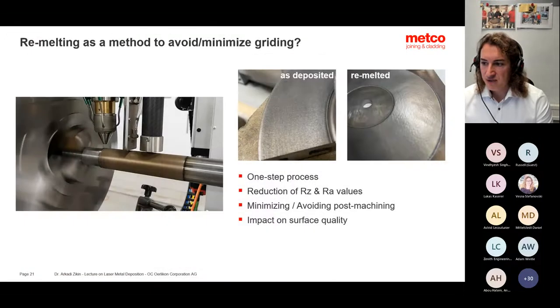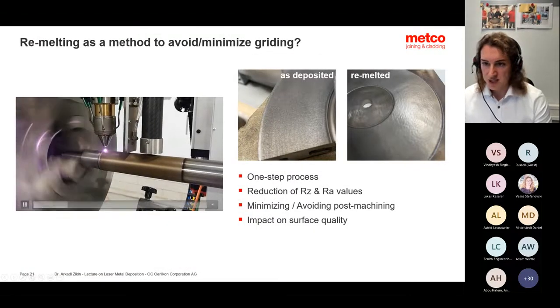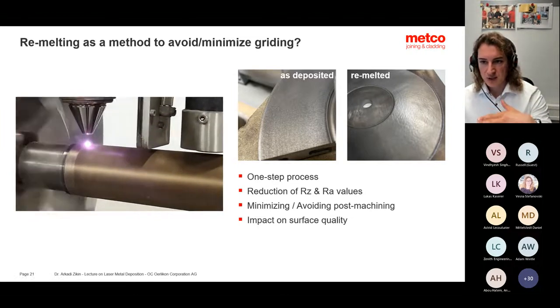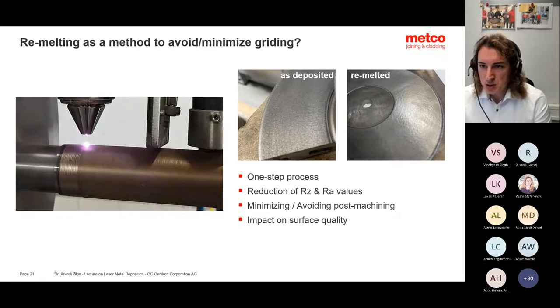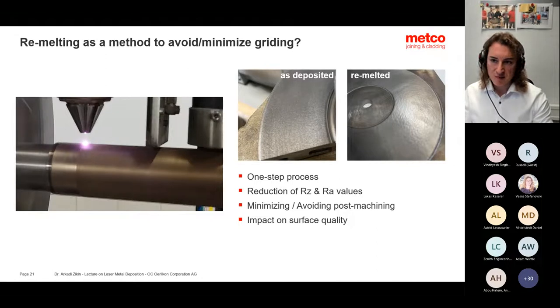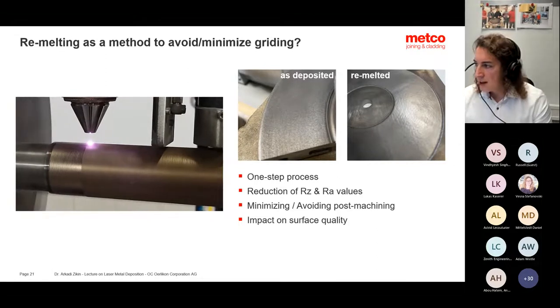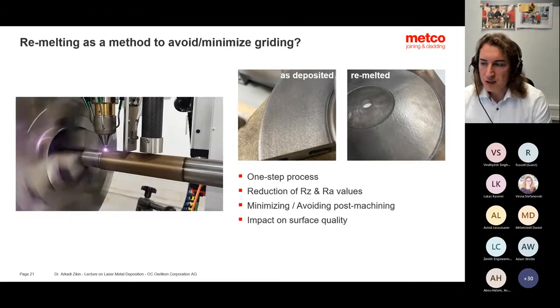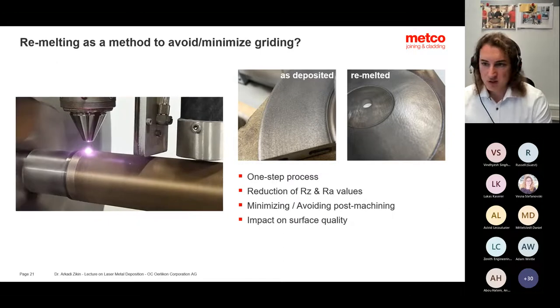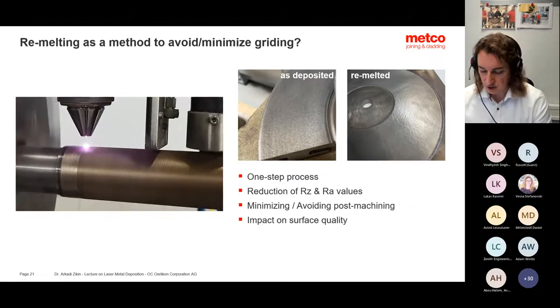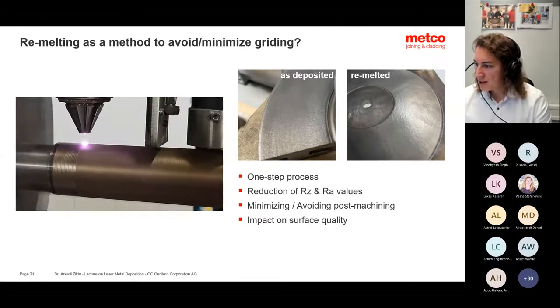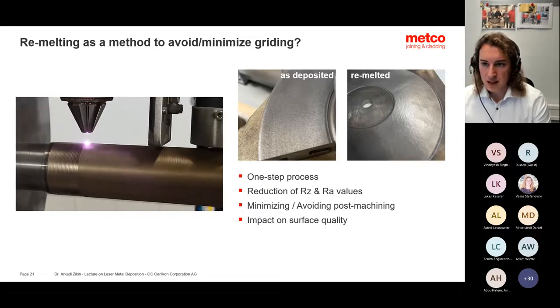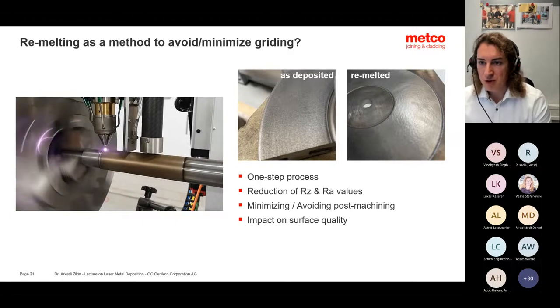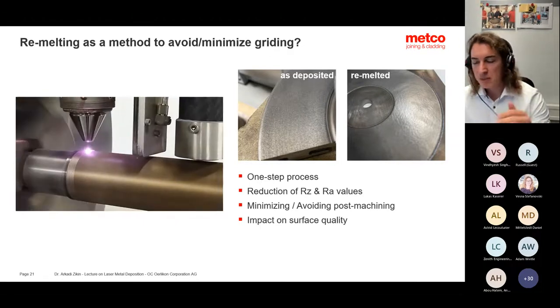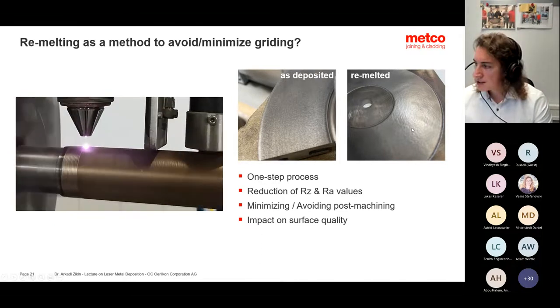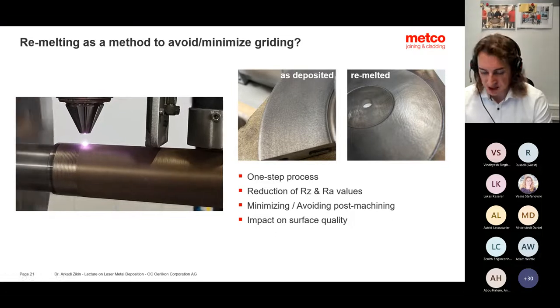And you can also move one step further. By doing that, you can, for example, remelt the surface using the same process without interaction with powders. And the main advantage you can get out of this is that you just smooth the surface, taking certain asperities away or some stuck powder particles. And for certain applications, you can completely avoid any type of post-treatment if a surface quality of something like Ra 5 would be enough for you. I believe there is still a lot of work moving in that direction. And we also recognize that working with laser surface remelting requires process understanding and development steps. But at the end of the day, you can get results which look pretty similar to this. And it's impressive.